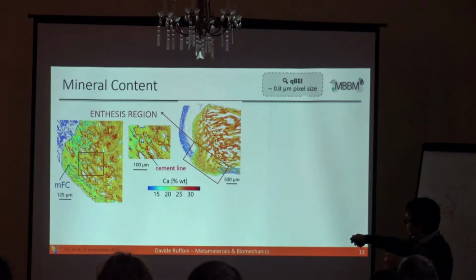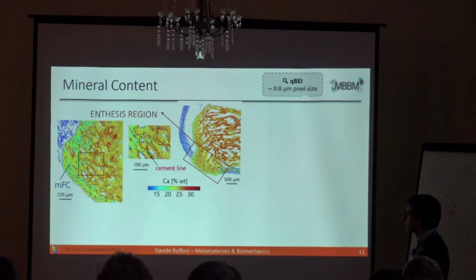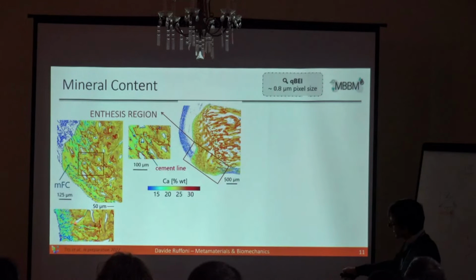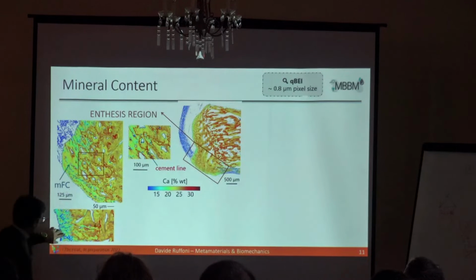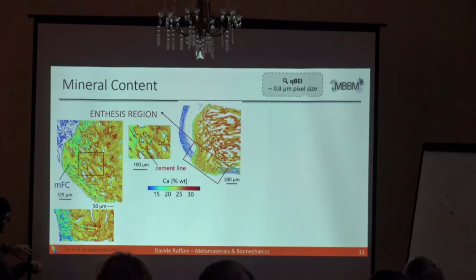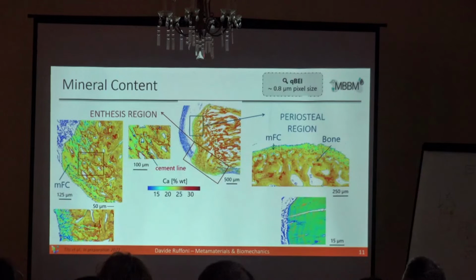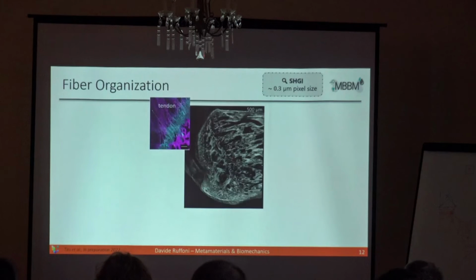So there are specific compositional modifications to glue these two tissues together, and also we see that there are fingers of fibrocartilage penetrating very deep in bone. So it's an interface which, as I said before, is highly interdigitating, to increase the anchoring properties like tree roots, if you want to see it this way. To some extent, this is also true in fibrocartilage, but less. Due to the higher forces which are transmitted here at the tendon insertion, we see that fibrocartilage tissue is anchoring very deep in bone to actually anchor the tendon also. And that's basically it.